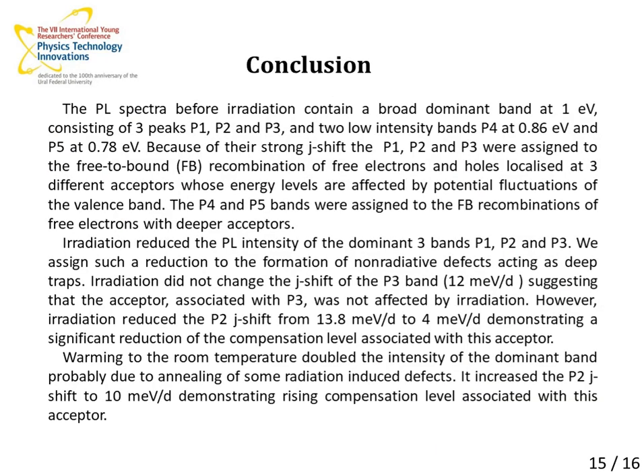In conclusion, I'd like to say that irradiation reduces the photoluminescence intensity of the dominant band, and we assign such a reduction to the formation of nonradiative defects acting as deep traps. Irradiation did not change the energy shift of the third band, suggesting that the acceptor associated with this band was not affected by irradiation.